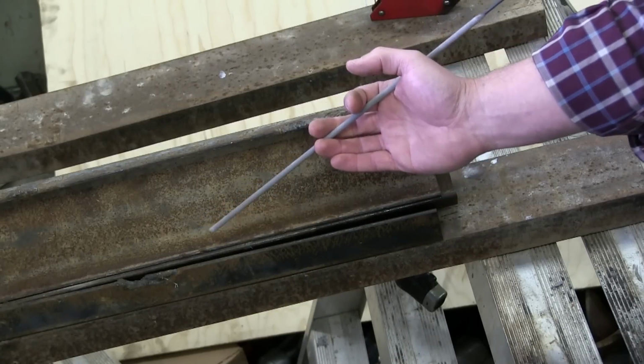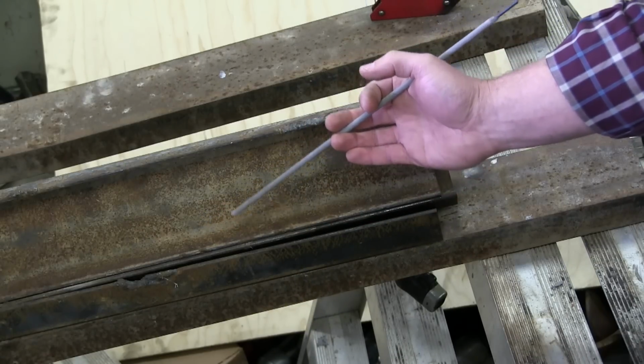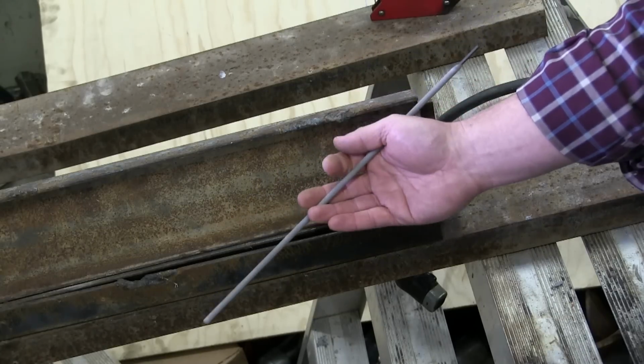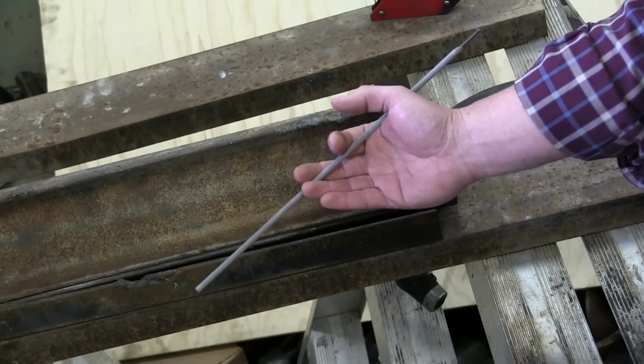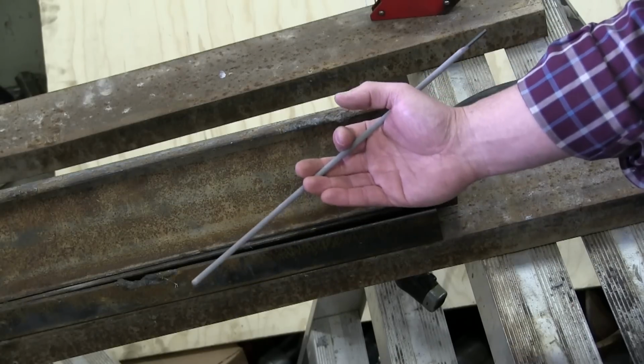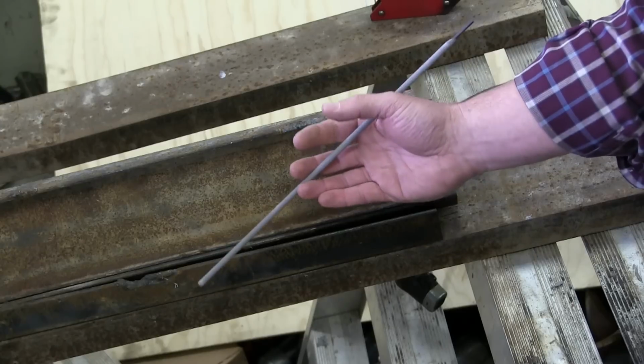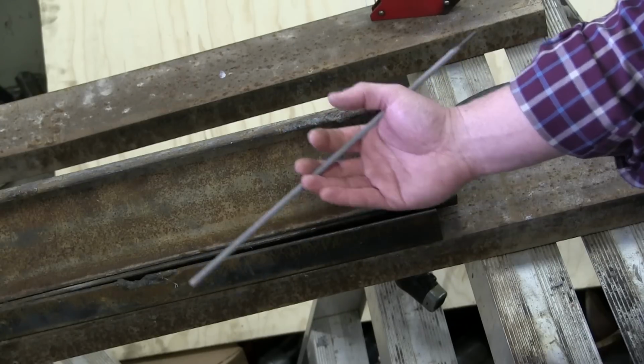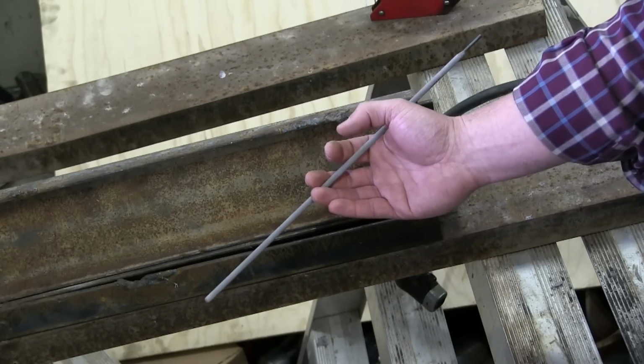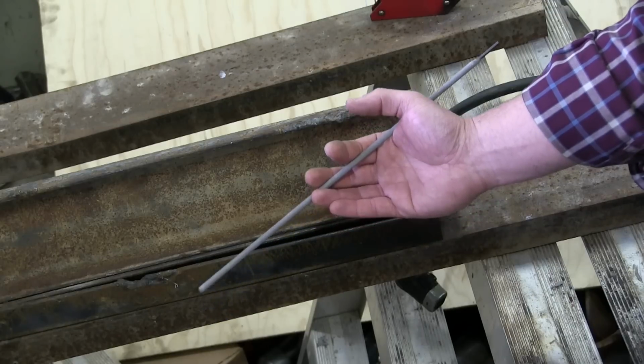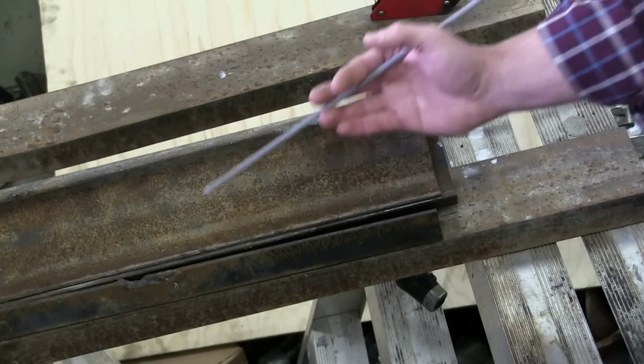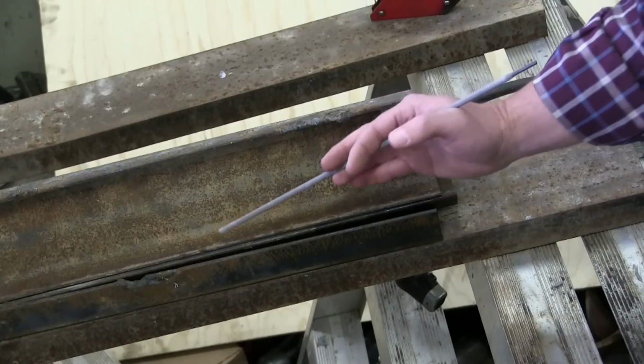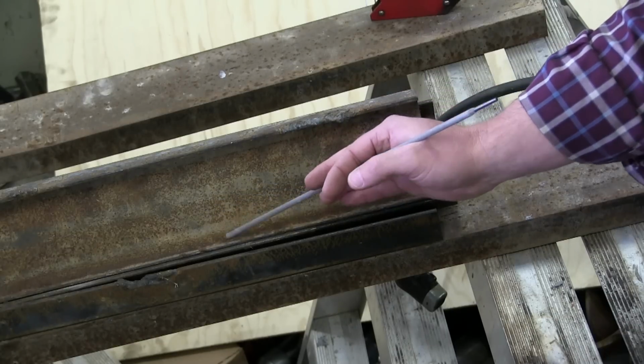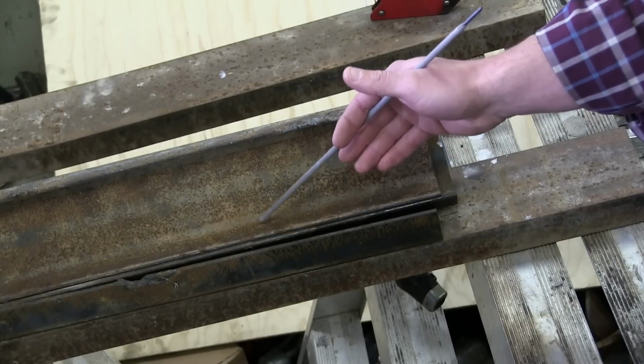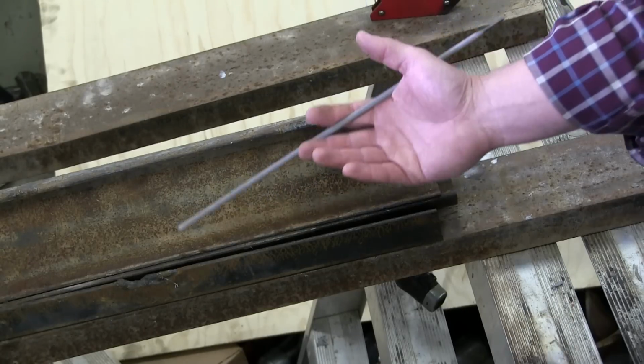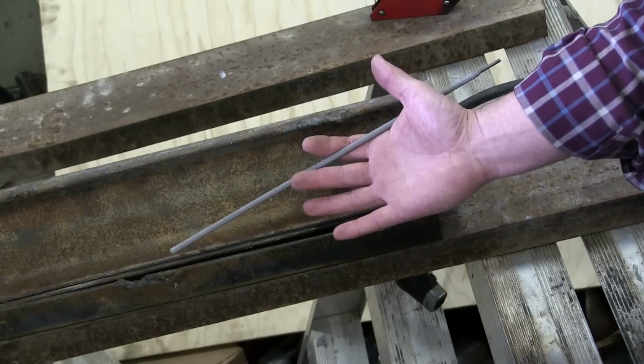And that's one of the things that makes welds, especially field welds, break quite easily, is having water or hydrocarbons around, because it puts hydrogen into the molten steel, and then when it solidifies, hydrogen comes out of solution, makes these little hydrogen gas pockets, makes cracks in your weld. So this 60-10, the long, the short, and the curly of it is, this 60-10 is good for scabby welds. So if you get paint or whatever on there, you want to use 60-10. Even though it's uglier, it's going to be stronger than a jet rod or a 70-18.